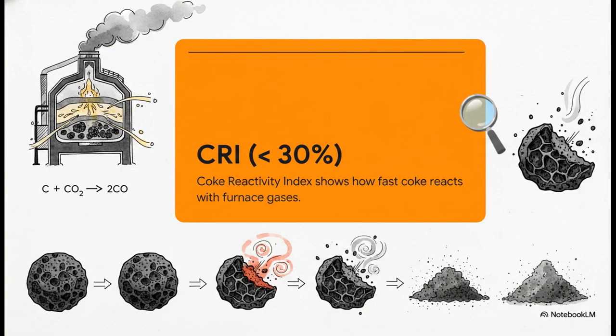Now for the really heavy-duty metrics. First up is the Coke Reactivity Index, or CRI. This measures how fast the coke reacts with furnace gases. We need a CRI of under 30%, period. If it's higher, it reacts with carbon dioxide way too fast and degrades prematurely in the upper, cooler parts of the furnace, rather than surviving down to the bottom where we really need it to do its job.